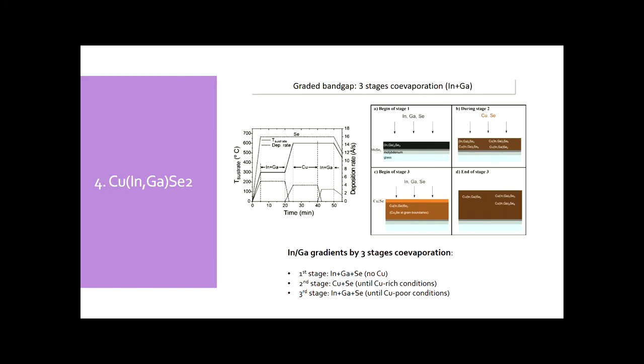And this works very well, and in this technology it can be achieved by gallium back and front grading, so more gallium at the back and more gallium at the front, or gallium with indium and sulfur and selenium, more gallium at the back, more sulfur at the front. And both of them work very well.